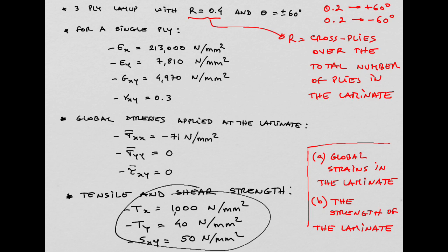And then we will define a factor of safety from this balance between these two: the maximum it can carry and the stress that is installed in that ply. And then, as the name says, a very high factor of safety means you can start questioning, do we really need to have the ply with this orientation? Because it's on the very safe side, it means our laminate is not optimized, so I can get rid of this ply, or I can define a different orientation.